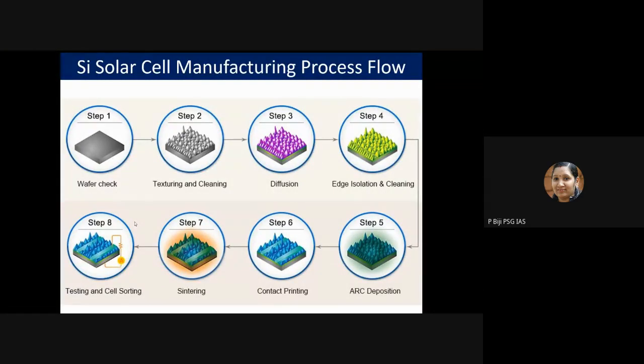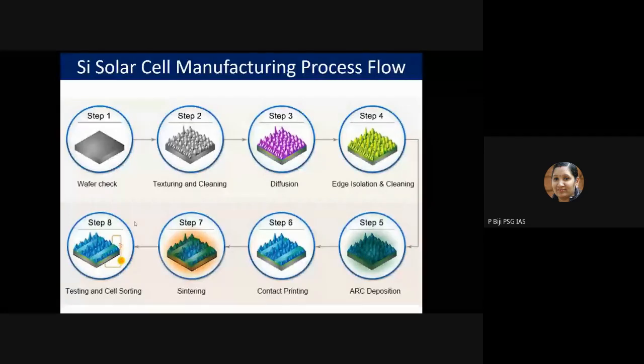ARC is the anti-reflective coating. After washing, these wafers can be processed for deposition of the ARC coating, basically a thin film of silicon nitride. Silicon nitride is commonly used, and of course titanium dioxide is also used in some cases, but the most common ARC coating is silicon nitride. At that stage, the color of the solar cell changes by varying the thickness of the ARC coating. If you see a silicon solar cell, almost everything will be in blue shades, different shades of blue. That means the thickness of this ARC coating, the silicon nitride thin film, is varying. Depending on that color, cell sorting happens.